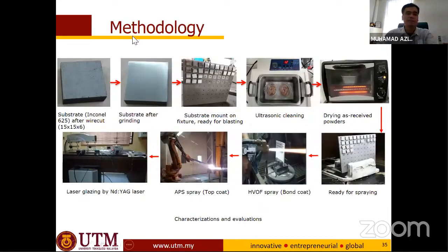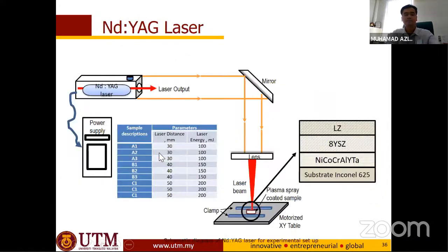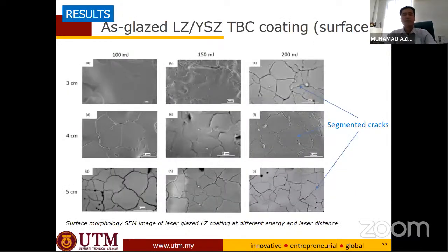All right, this is the sample, this is the methodology. We have the substrate, Inconel, for example, a nickel superalloy. We grind, we blast, and then we clean and dry, and then this is spraying, and then we coat the bond coat, and then we coat the top coat, followed by the laser glazing. All right, so this is our laser. We use an Nd:YAG laser, and we optimize the laser distance and the laser energy. So this is currently in progress. I can say it's still in progress, but it looks promising.